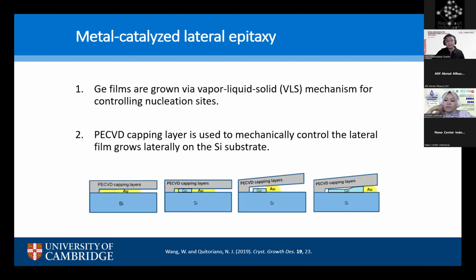And the process is as follows. First, you prepare your microcrucible, and then you bring it to your epitaxy chamber, CVD for example, so that when you introduce your precursor gases, the germanium will crack preferentially on the gold catalyst inside the capping layers, and then the gold will agglomerate. And as you keep dosing your reactor, your germanium crystal gets thicker and thicker, and due to the presence of the capping layers, the germanium is forced to grow horizontally, laterally. By the way, this technique is quite well known in the nanowires community, basically using gold as a preferential nucleation site. The gold is always in the liquid state during the growth and guides the nanowires' unidirectional growth.